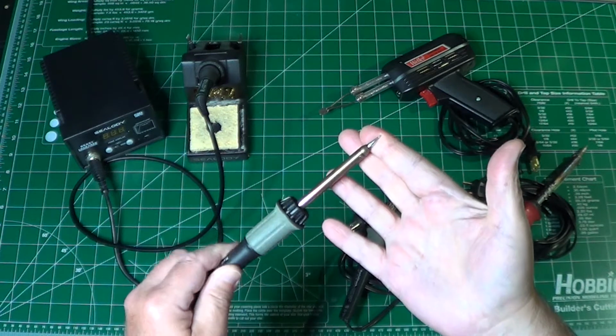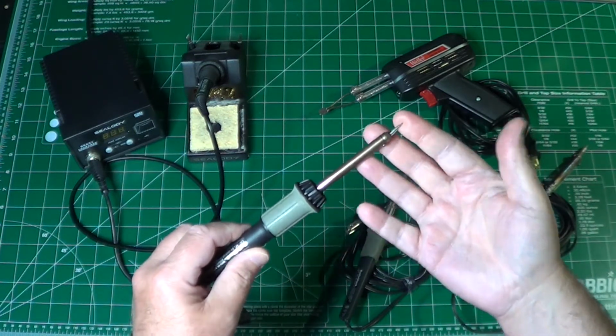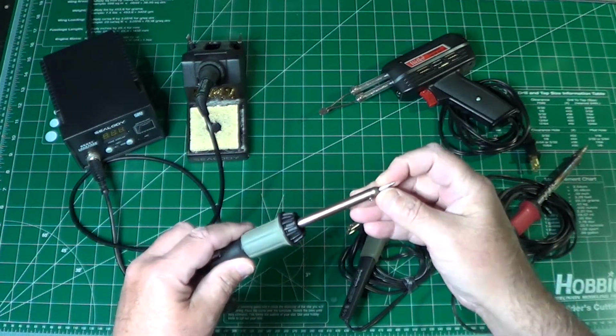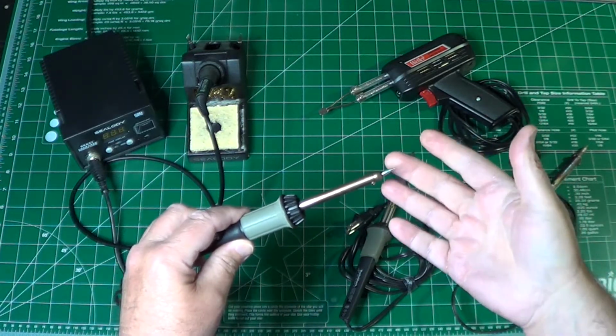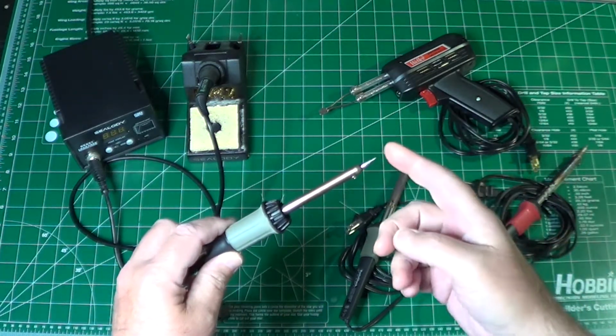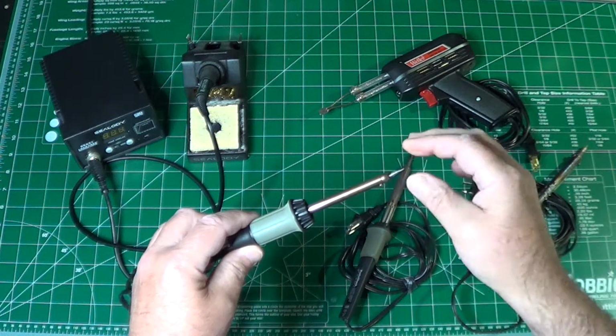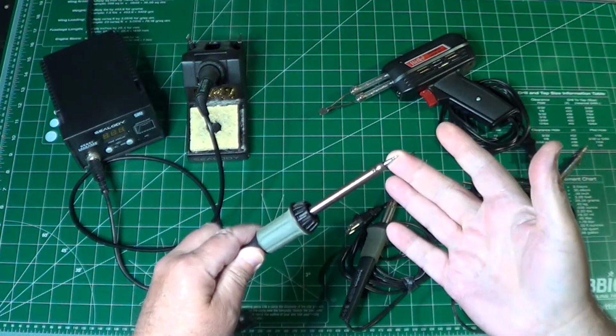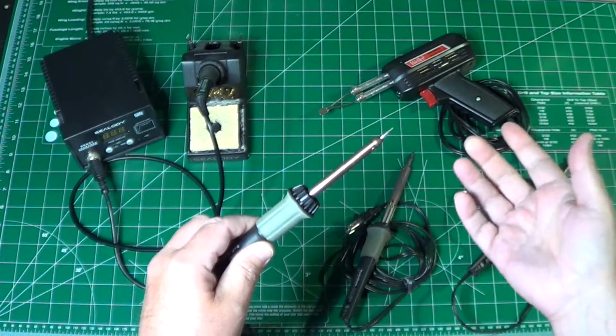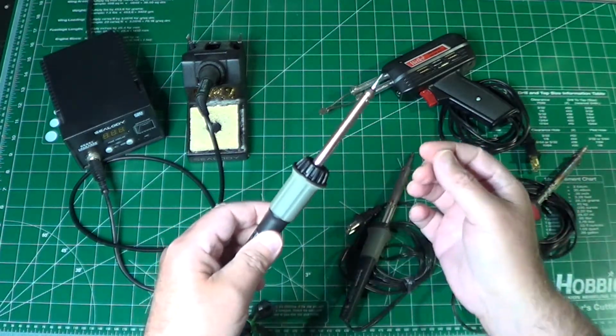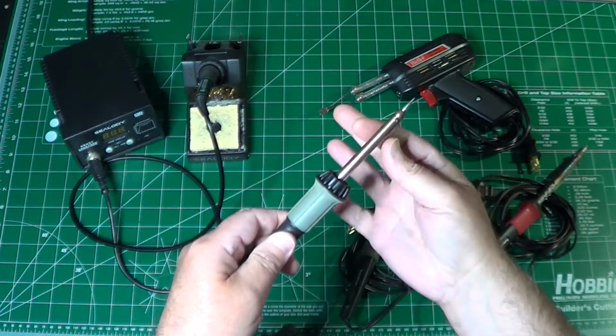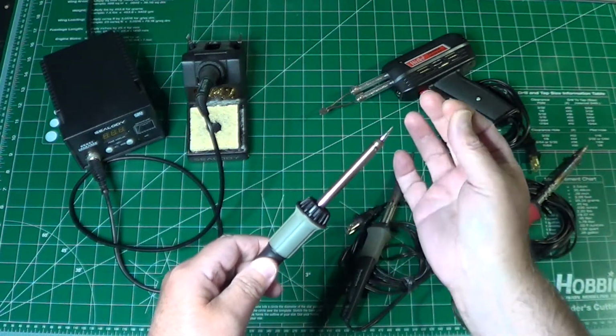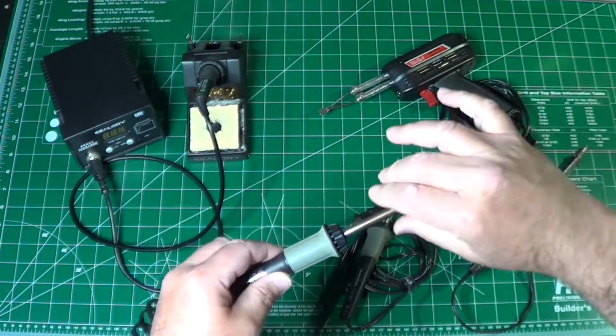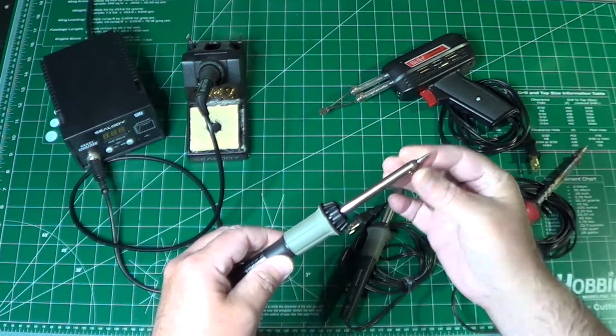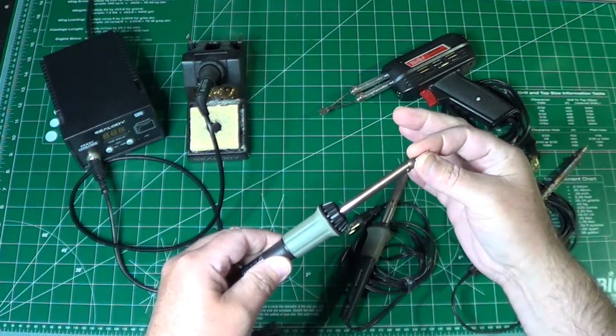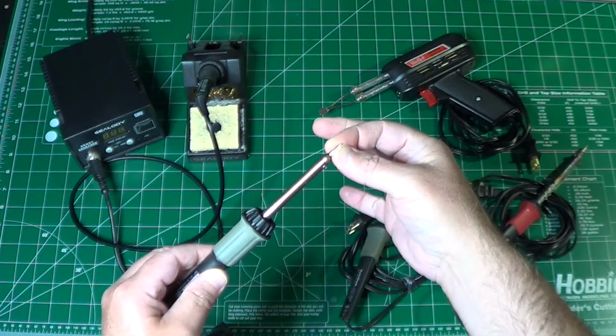The corrosion happens during the usage of the iron, and it is caused by the tin and lead of the solder that chemically react with the copper of the tip to form an alloy that sometimes also creates a brittle residue on the tip itself. Cleaning the tip periodically removes the alloy, but also erodes the copper tip a little bit at a time. The heating element of this kind of soldering iron is basically a resistor located inside this tube, which is in contact with the tip to transmit the heat to it.